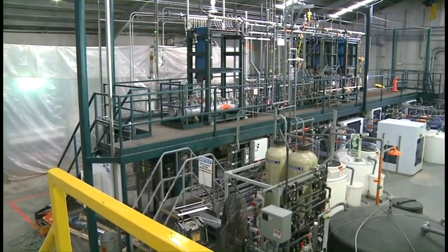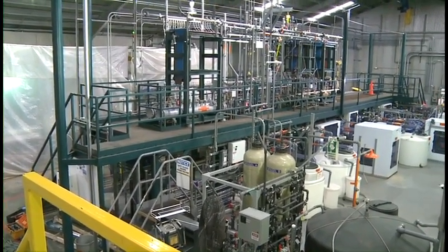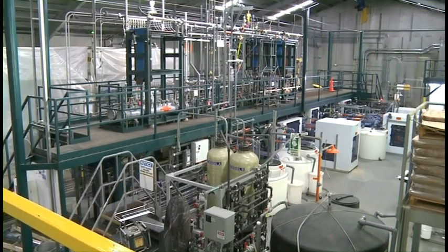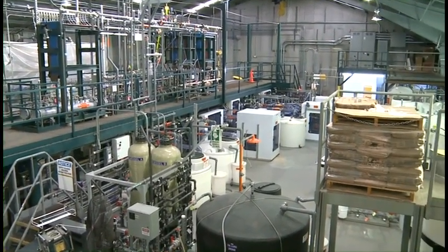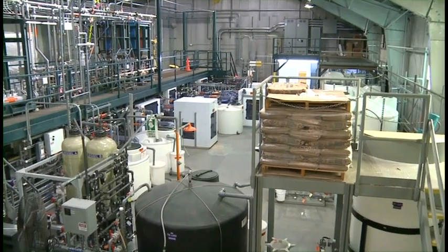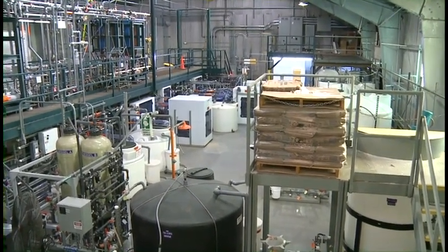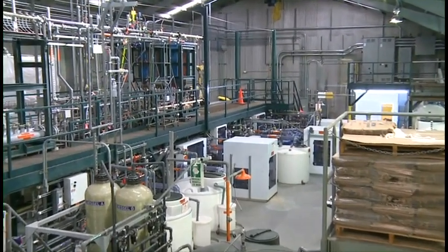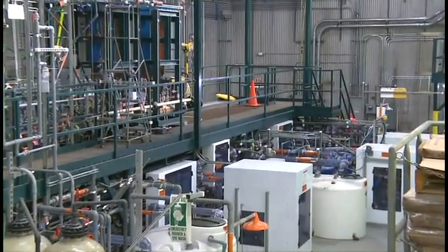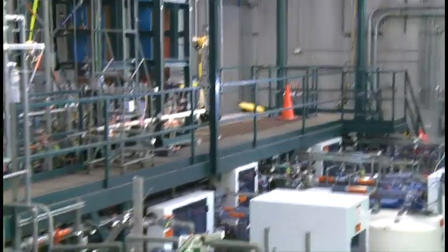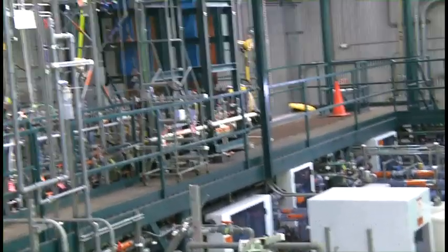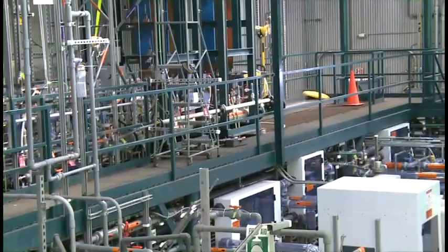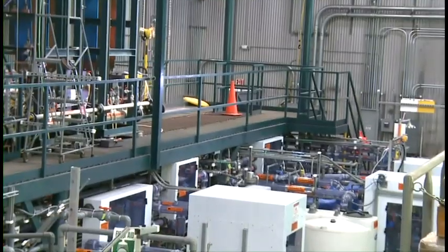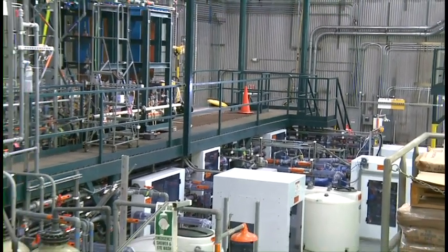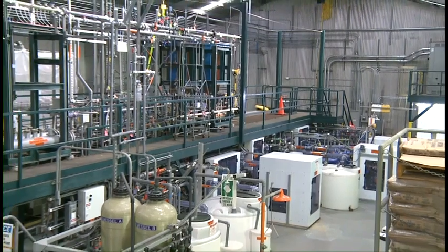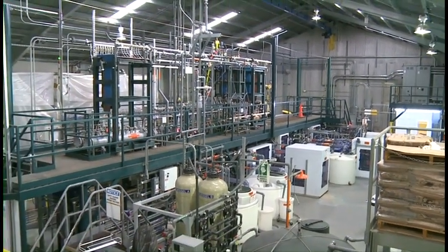So this is our electrochemical pilot plant. This facility makes one of the critical ingredients in our process, which is the alkalinity. We need alkalinity to be able to capture CO2. Alkalinity you can think of as a base, and CO2, carbon dioxide, is a weak acid. So this is generating the base and allows us to do the absorption reaction. And what we've done is we've pioneered a new technology based upon electrochemistry that would allow us to generate that base at very low energy requirements. We call it ABLE for short, alkalinity based on low energy. But it's a Calera pioneered technology specifically for generating this material.